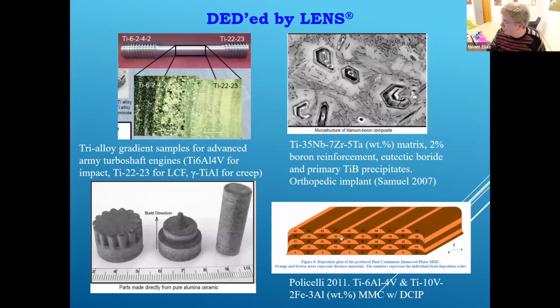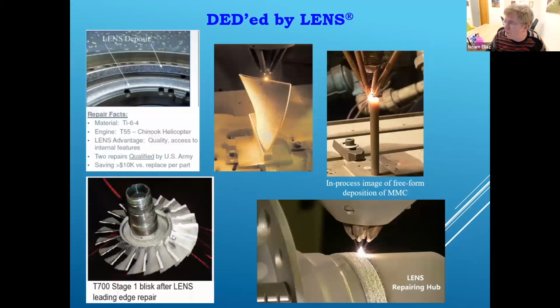At the bottom, you can see from another thesis, the processing of DCIP, dual continuous interpenetrating phases. This is a kind of composite where the matrix and the reinforcement ratio is approximately 50-50. And here what they did, they used mechanical design simulation to predict the mechanical properties that one will obtain with different orientations of the two materials, and then they quickly went to the lab and printed them. At the bottom left-hand side, you see an example of alumina, small parts. It's challenging to print large ceramic particles.